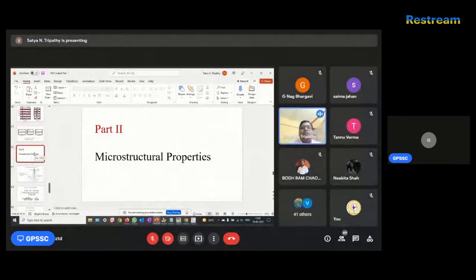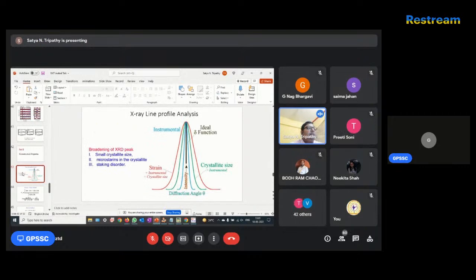Next is your microstructural properties. Microstructural properties mean your crystallite size, strain, all these parameters. Next, one of the most important techniques is X-ray line profile analysis, right? In X-ray line profile analysis, from a theoretical point of view, you will have XRD data, but that data will broaden based on different parameters like crystallite size, instrumental strain, and lattice strain. All these affect and broaden the peak.